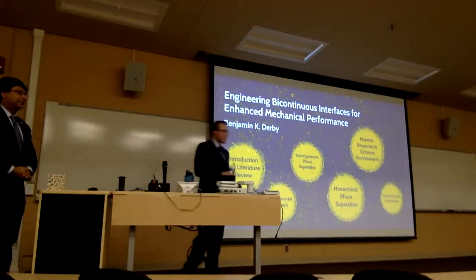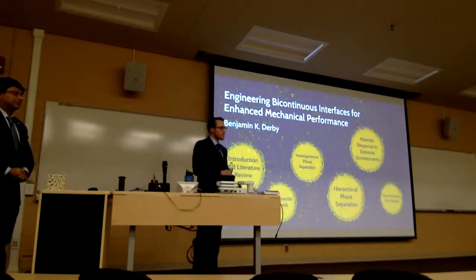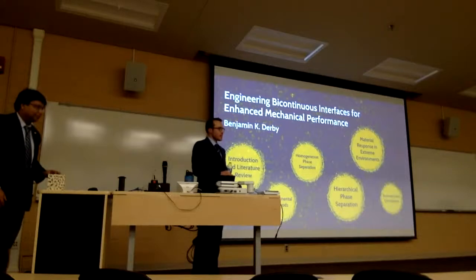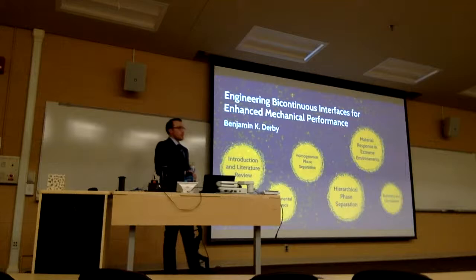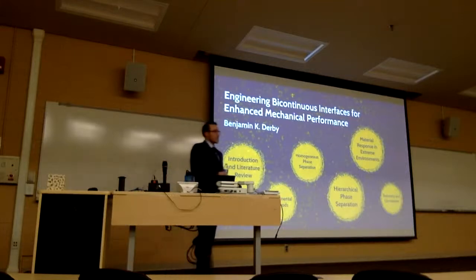So basically at these different rates, you get sort of some metastable states. And you say you actually have an amorphous copper state in the first material? There's no amorphous state, but it does have a BCC crystal structure at the lowest temperatures that we deposited at.